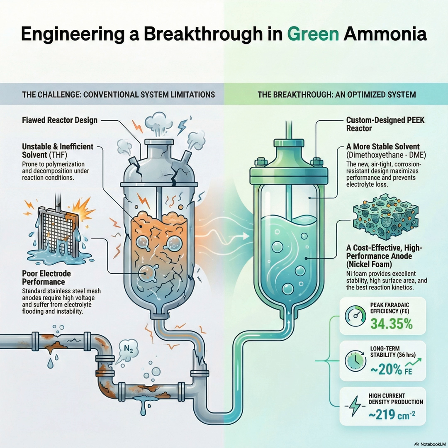And they pushed it even harder, right, to test its industrial speed. They did. They pushed it to a very high current density, negative 750 milliamps per square centimeter. Which means you're forcing a ton of electricity through it really fast, kind of a stress test. Precisely. And even at that stress level, the system held up. It achieved a really high ammonia partial current density of about 219 milliamps per square centimeter. The researchers said that's way beyond what previous studies have shown. It can run continuously, and it can run fast.